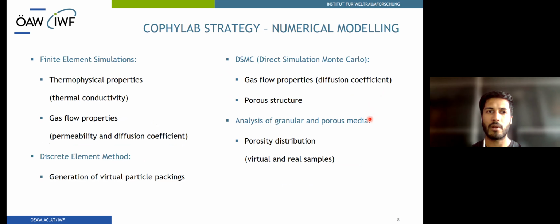As any other research campaign, Cophylab is also accompanied and complemented by various modeling activities. On the one hand, numerical models can be used to verify the measurements. On the other hand, they are very important for the application of the experimental results in cometary environments. Depending on the nature of the physical problem, we used various methods. To model thermophysical or gas flow properties, for example, finite element simulations were performed. The discrete element method is used to create virtual samples. These, in turn, are utilized in other simulations, such as the DSMC, which is a statistical method. Currently, we are also planning to create CT scans of several reference samples to compare their porous structure with that of the virtual samples.